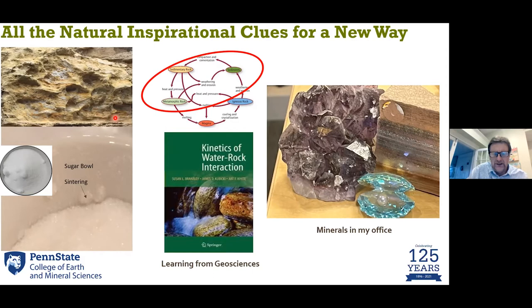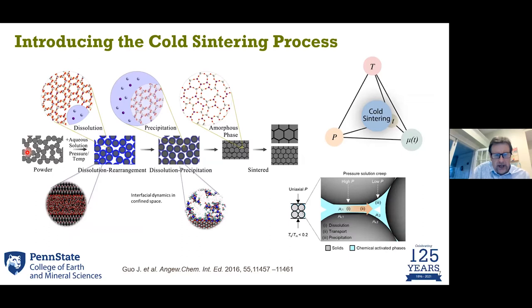Even sitting in a damp kitchen in say Scarborough in England at some time, looking at a sugar bowl, you can see that the crystals are undergoing a densification and sintering. All of these are clues that there may be a better way to sinter materials. So the basic process is the following. There is powder, we add a liquid transient phase, we apply a pressure, we add a moderate temperature, and as